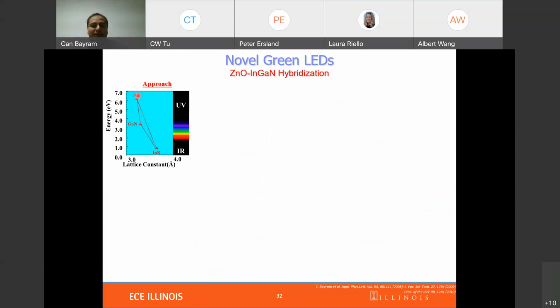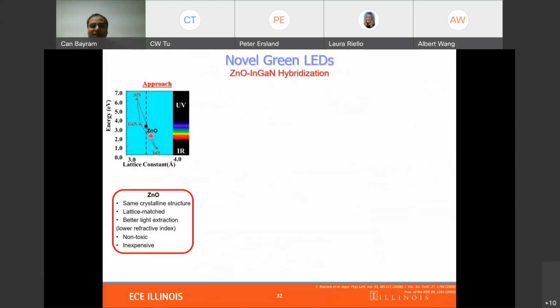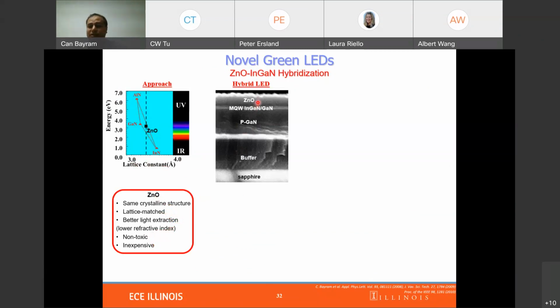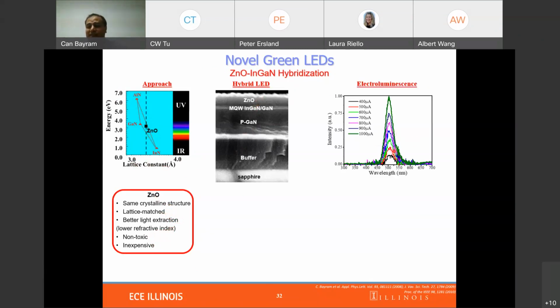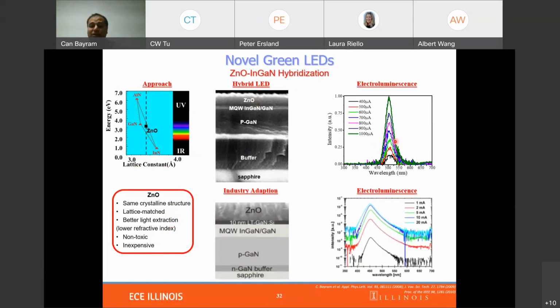Well, if you look at the energy lattice constant diagram of nitrides, we see that there is a material, zinc oxide, that has the same crystalline structure. It's lattice matched to the indium content solutions, and you can have better light extraction, and it's non-toxic and inexpensive. So one of our designs employed zinc oxide on top solutions where we achieved one of the purest green emitters in terms of spectral quality.